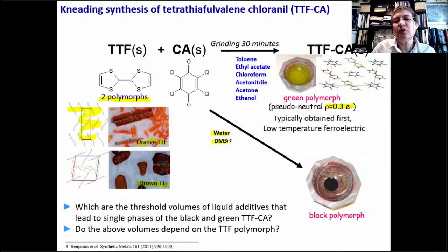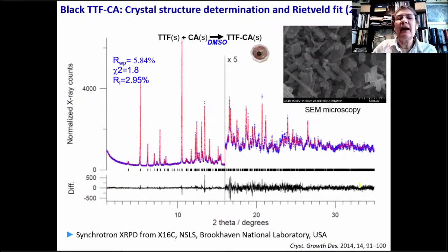Okay, so it was seen that water and dimethyl sulfoxide as liquid additives led to the black form, that was thought to be ionic. So we used sufficiently large quantities of dimethyl sulfoxide as a liquid additive to produce single phases of this material. And we could collect synchrotron X-ray powder diffraction data at X16C, Brookhaven National Laboratory, to determine the crystal structure from X-ray powder diffraction. So here, the effect of a liquid additive has been that it allowed us to prepare single phases of this poorly studied polymorph, and the phases were sufficiently crystalline to be able to determine the structure from powder diffraction.